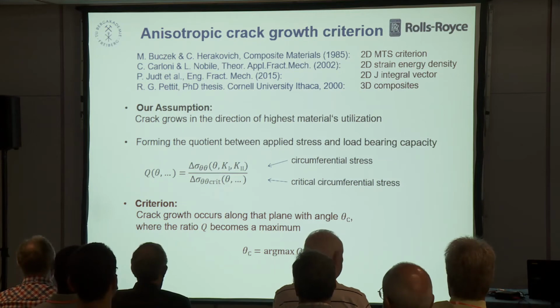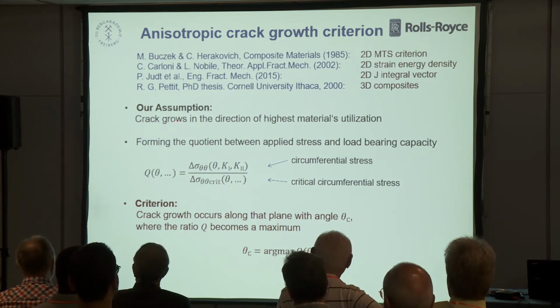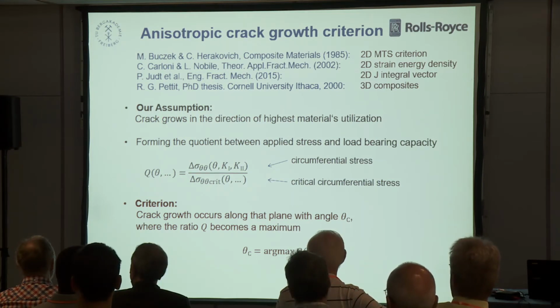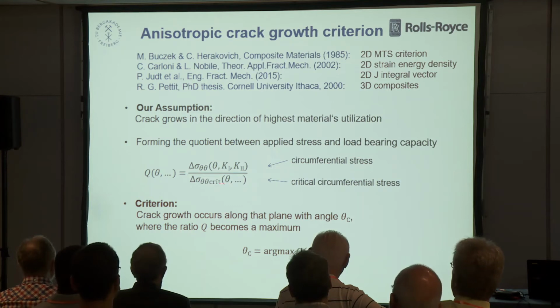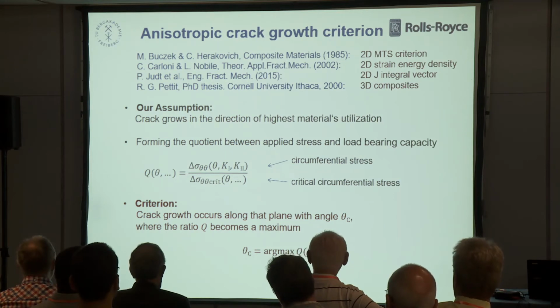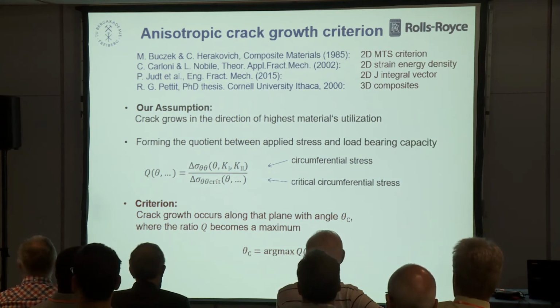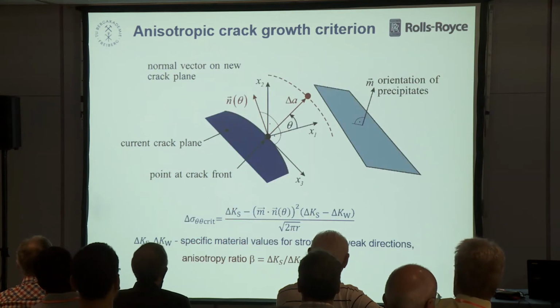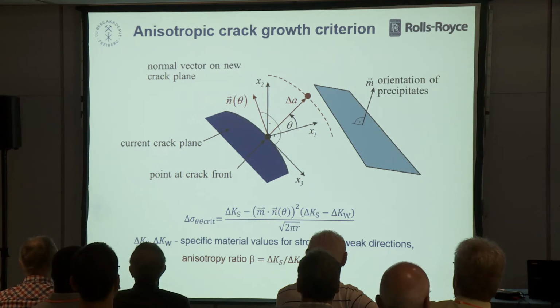So we had to find a new criterion. And our idea is the following. The crack goes in that direction where the stress is highest compared to its resistance. So we form a quotient between the applied stress, which is the same as in the previous formula, the circumferential stress, and a function which describes the resistance to crack growth in every direction theta. When this ratio has a maximum, the crack will follow this direction. So, loading compared to resistance has a maximum. In our case, it is 3D, so it's a little bit more complicated. Here we have one point of the crack tip.